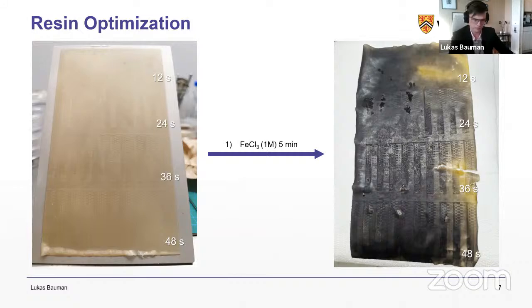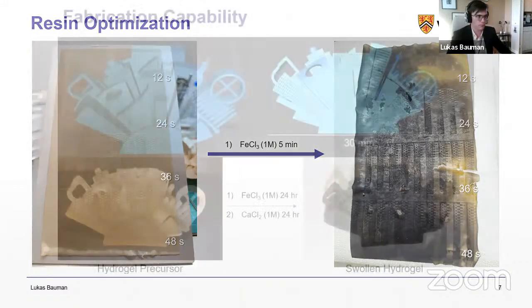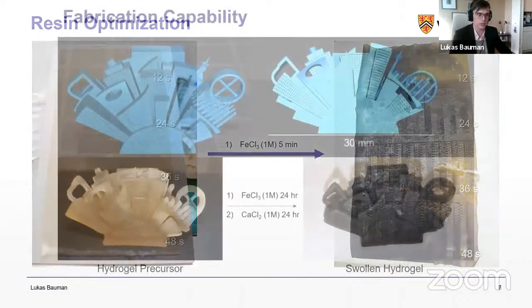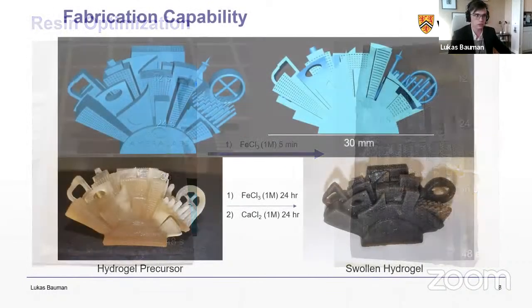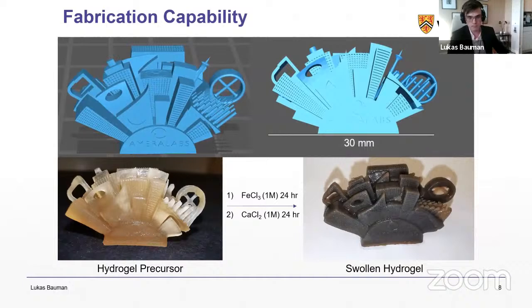So next we have the fabrication capability. This is a 3D model that's available for free online through the resin company Amerilabs. What we did was we used this to test the resolution of the hydrogel precursor resin because it has a lot of overhangs, thin members, and things that would be difficult to print through extrusion-based printing. And so here's an example of the actual printed part. It's quite small, only about 30 millimeters long.